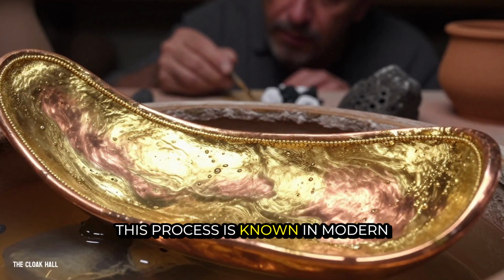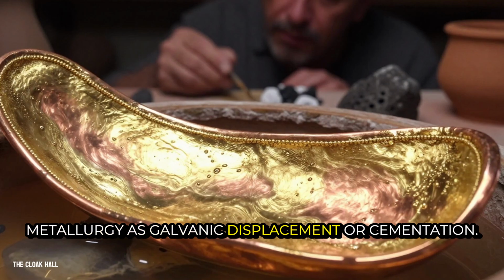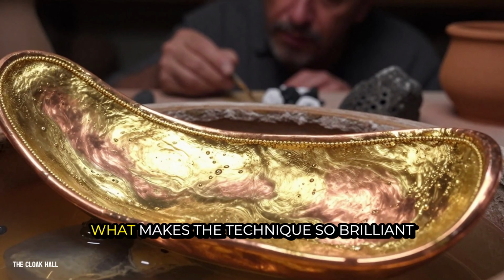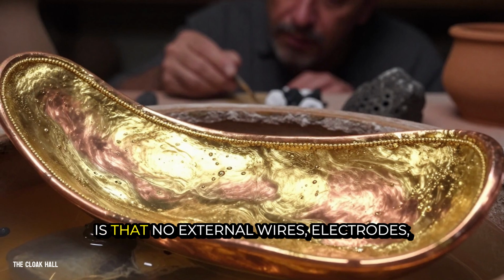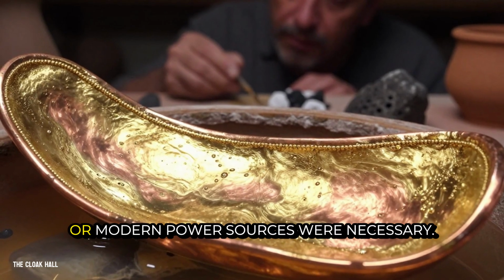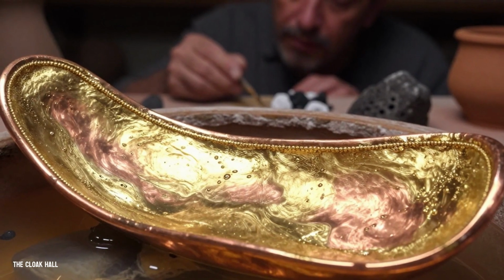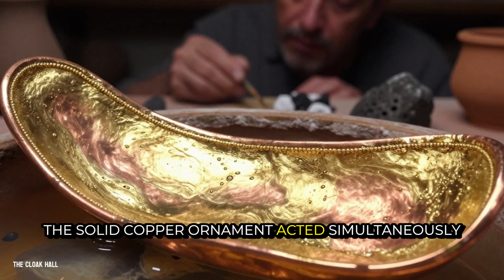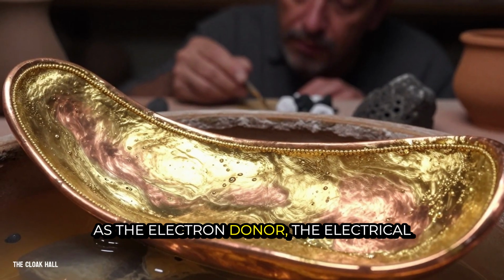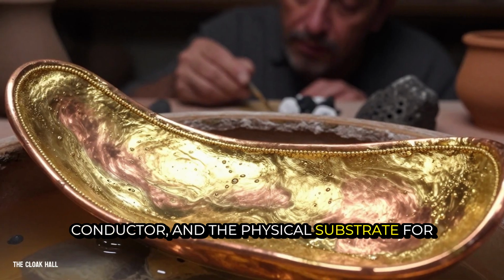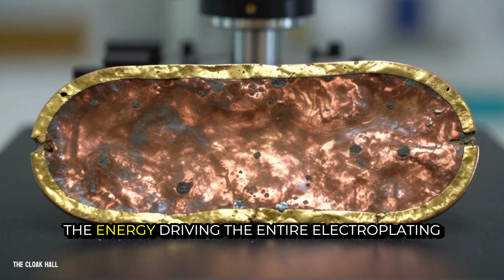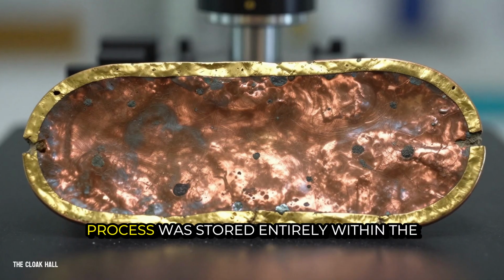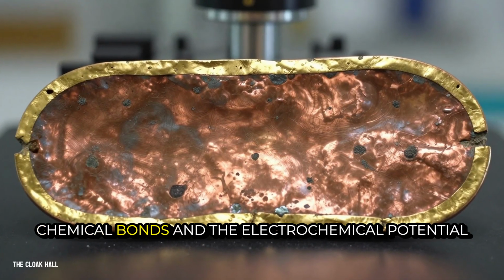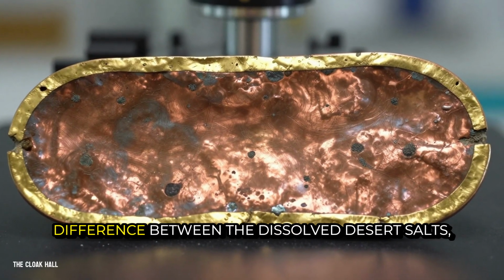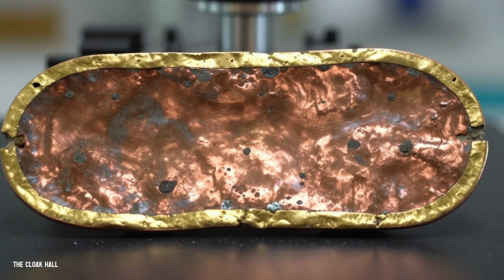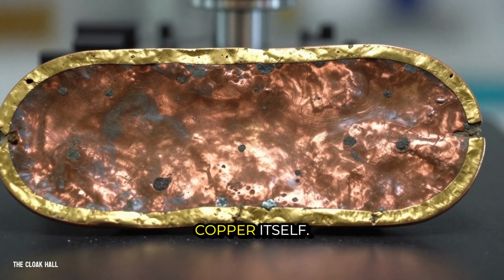This process is known in modern metallurgy as galvanic displacement or cementation. What makes the technique so brilliant is that no external wires, electrodes, or modern power sources were necessary. The solid copper ornament acted simultaneously as the electron donor, the electrical conductor, and the physical substrate for the plating. The energy driving the entire electroplating process was stored entirely within the chemical bonds and the electrochemical potential difference between the dissolved desert salts, the gold ions, and the metallic copper itself.